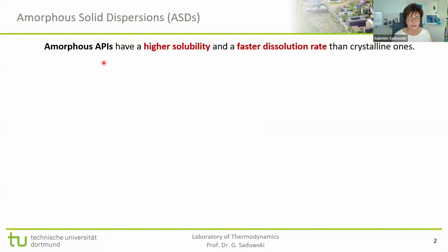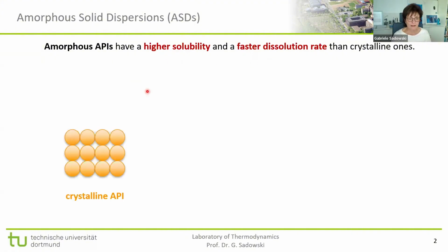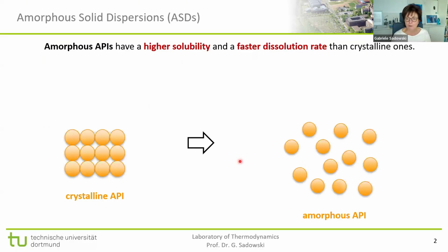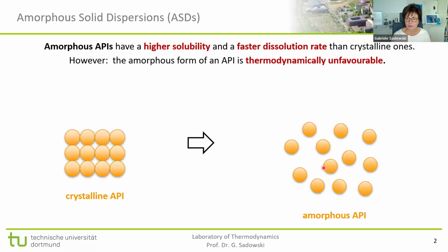What is found and can be also shown is that amorphous APIs are better than the crystalline ones in terms that they have both a higher solubility in water and also a faster dissolution rate. And that makes a huge difference when we take a tablet containing those molecules. So the idea is to keep the APIs, which are usually crystalline at room temperature, amorphous. But the problem is that the amorphous state is the thermodynamically less stable one, and so the APIs want to recrystallize. So we have to avoid this.